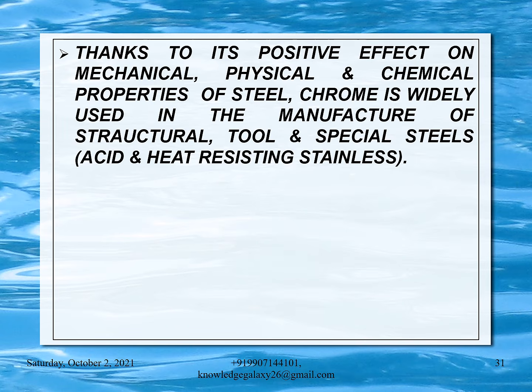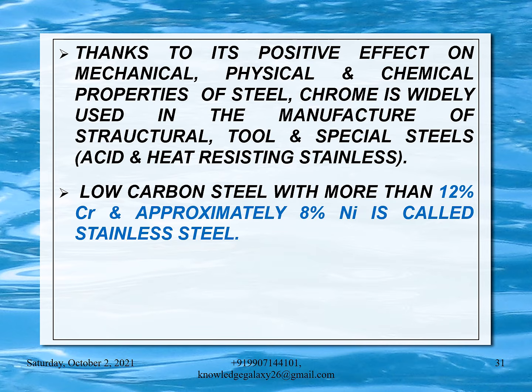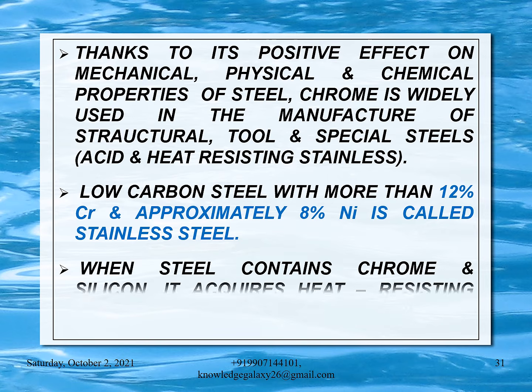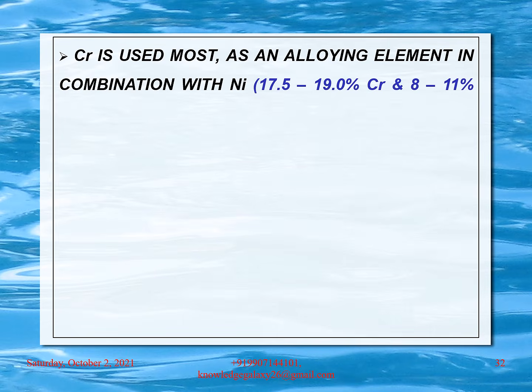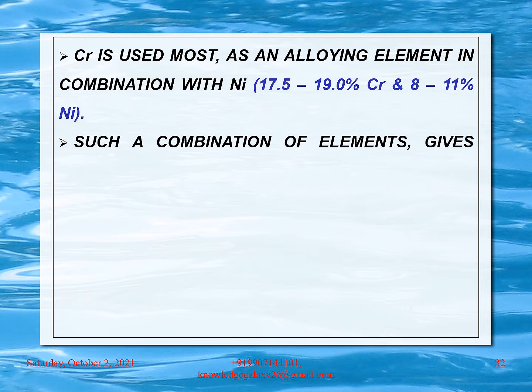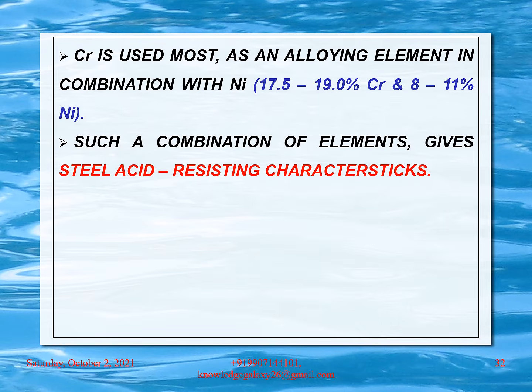Thanks to its positive effect on mechanical, physical, and chemical properties of steel, chrome is widely used in the manufacture of structural, tool, and special steels, acid and heat resisting stainless steels. Low carbon steel with more than 12% chromium and approximately 8% nickel is called stainless steel. When steel contains chrome and silicon, it acquires heat resisting qualities. Chromium is used most as an alloying element in combination with nickel, 17.5 to 19% chromium and 8 to 11% nickel. Such a combination of elements gives steel acid resisting characteristics.